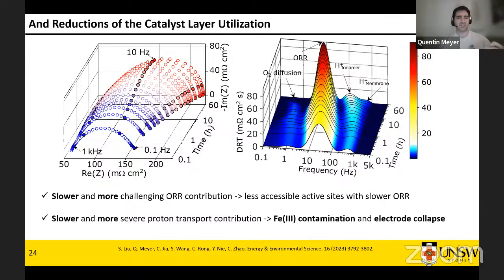Highly active, but extremely unstable material, active sites, that could be the ones over here. And then you have some much more thermodynamically less active sites. These could be these ones who basically you switch from one predominance to this one. And there's been a lot of characterization on this, confirming this, so we could very much be looking at both phenomena.